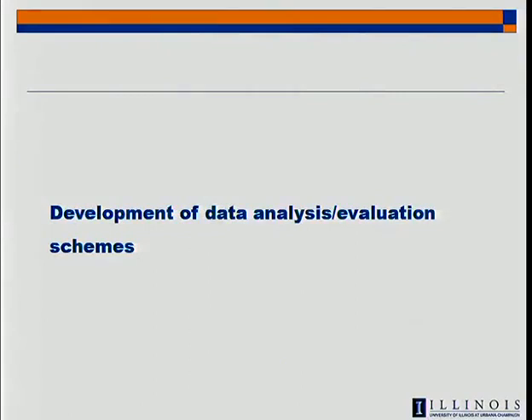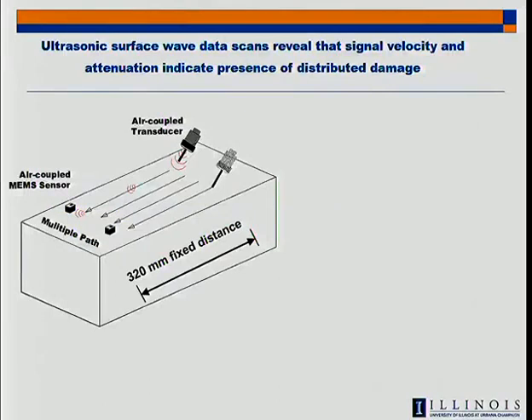How do we now take those signals and make sense of them? Well, the simplest way is to just measure how long it takes for them to travel from A to B on the surface and get their velocity, their speed. Because as I mentioned on that earlier slide, the speed is tied to mechanical properties. Stiff, strong, resilient materials carry waves faster. Porous, cracked, compliant materials carry waves slower. It all has to do with the atomic bonding and the interaction between molecules. It's very straightforward. Dense materials typically. So one of the easiest things to do is just measure the speed at which it travels across. And so I'll show you some results now that show how we can characterize that.